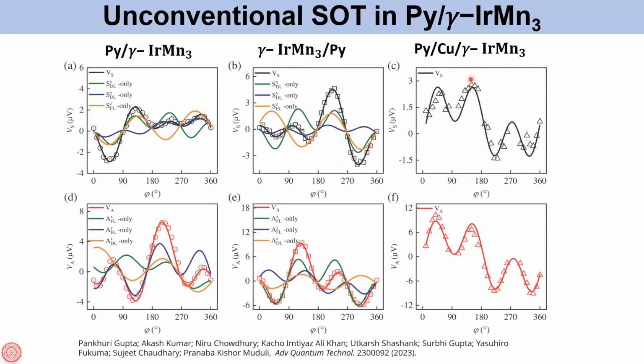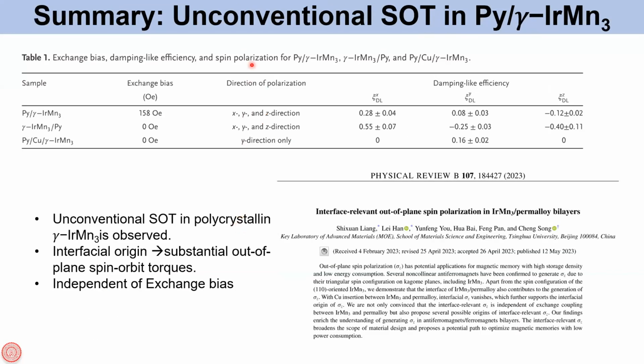And when you have copper, then you have the standard sin 2φ cos φ dependence, indicating that here it is conventional torque, whereas it is unconventional torque in both these other cases. And in this case it is attributed to the interface. So this is a summary.